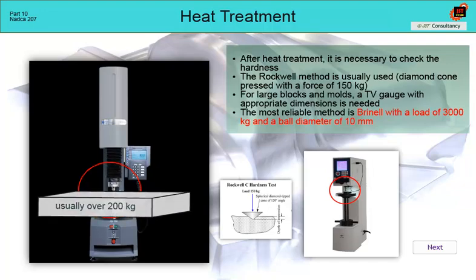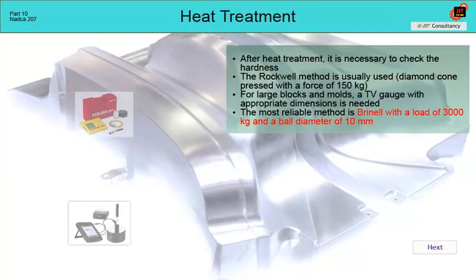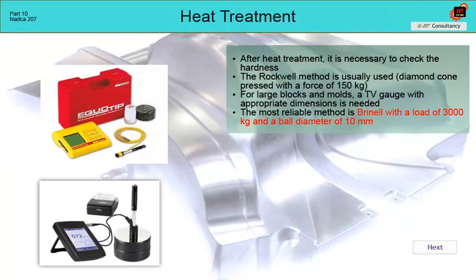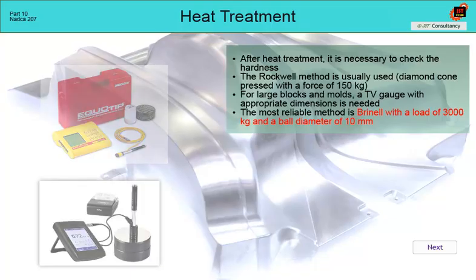Therefore, other alternative methods are also used for hardness measurement in the form of portable hardness testers, measuring hardness based on ultrasound or reflection. However, these methods are not sufficiently accurate, if only because they measure hardness only in a thin surface layer of the hardened insert, which can be affected, for example, by local decarburization or other structural defects.